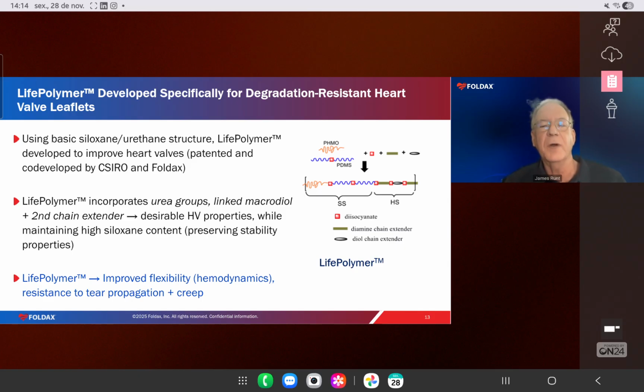And you can see on the top right the cartoon up there with the compatibilizer, the siloxane and the hard segments. And then it incorporates patented other chemistry that has other chemical groups in there, like ureas and a second chain extender. Again, that's not so important, but you end up with desirable properties for heart valves while maintaining a very high concentration of the siloxane units for biostability. So you're getting good mechanical properties, you're tuning in the characteristics that you want, and you're keeping the biostability associated with the siloxane units. So that's life polymer, right?